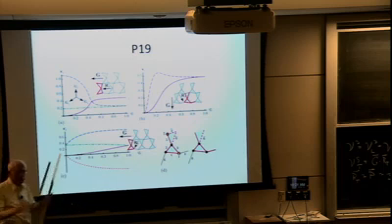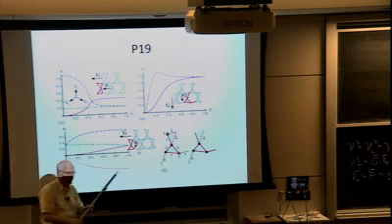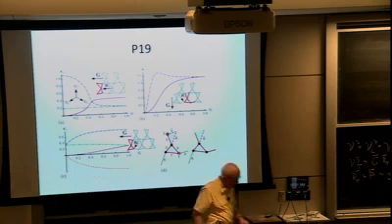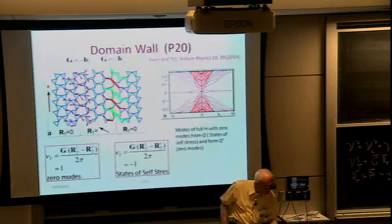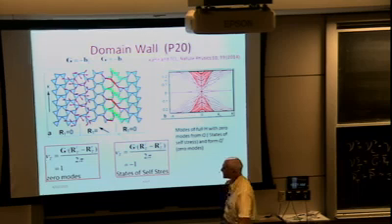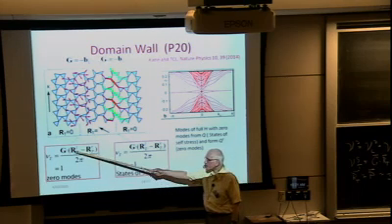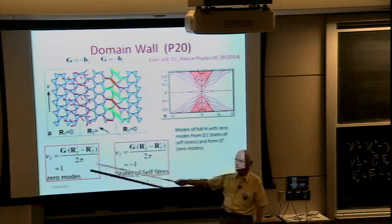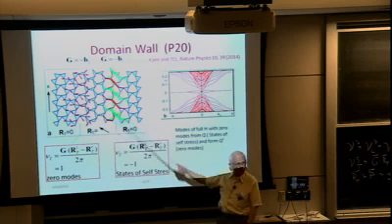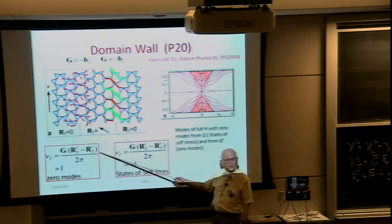And now I can put them together in the same way that we discussed with the one-dimensional model. And the total count then is the difference between the topological count on the left and the right, dotted into the G vector that characterizes the domain wall. We've lost the local part here.